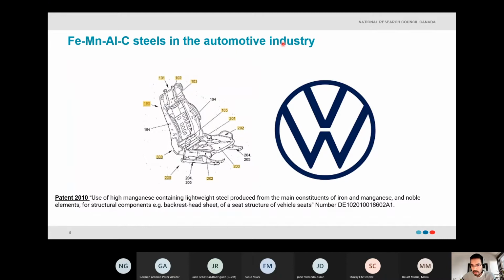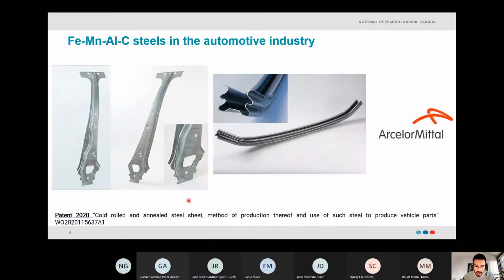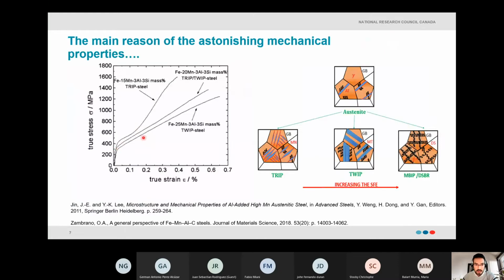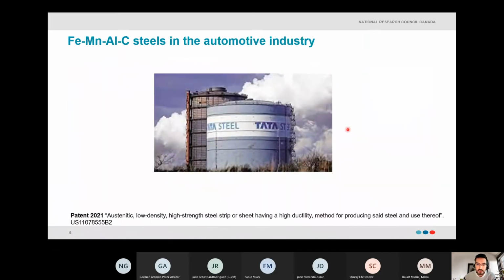In the automotive industry, for instance, Volkswagen obtained a patent in 2010 about replacement of conventional alloys for the seat frame. So they are using this kind of material for the seat frame. Similarly, ArcelorMittal patented in 2020 a method of production of these alloys for car body frames. The reason is that when there is a car accident or a crash, the high energy during that process can be absorbed by this material by strain hardening. So it becomes harder, while also providing some deformation. That's the main reason for this choice for producing this material.